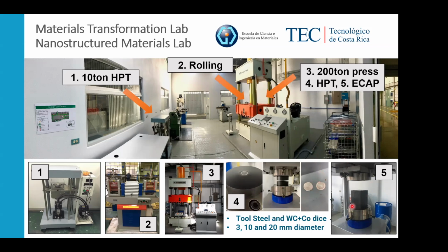We also have the capability to do ECAP, and we have just one ECAP die. It's either 90 degree or 120 degree, 10 millimeter diameter bars that we can press using roughly the same press, just exchanging the HPT die and using the ECAP die without applying any rotation. So this is our main processing capabilities, and mostly our 200-ton HPT machine is the most busy.